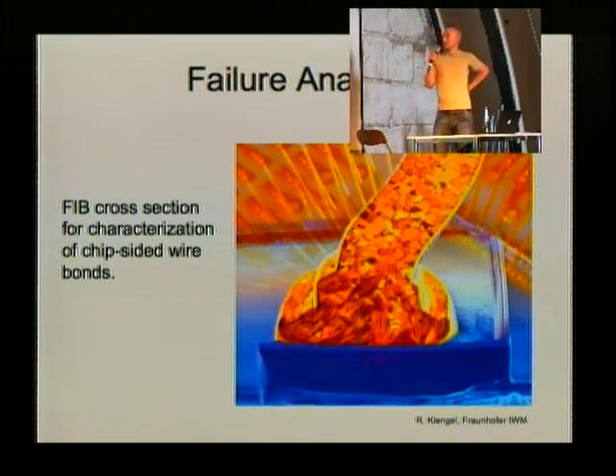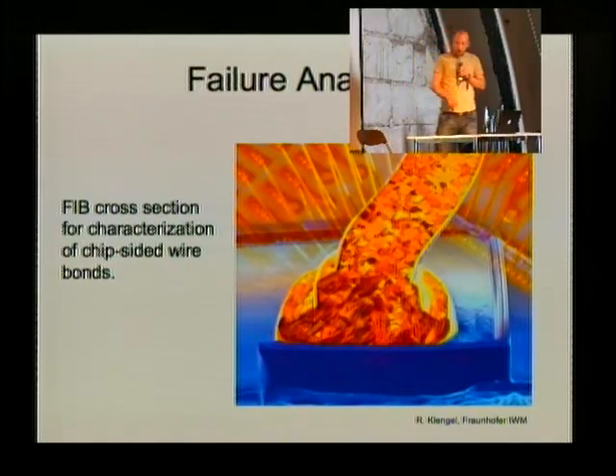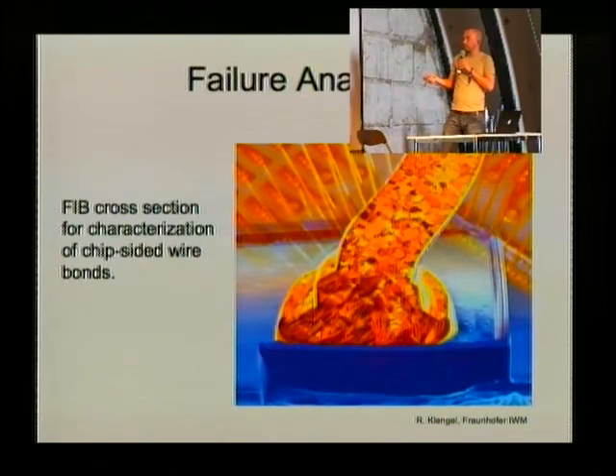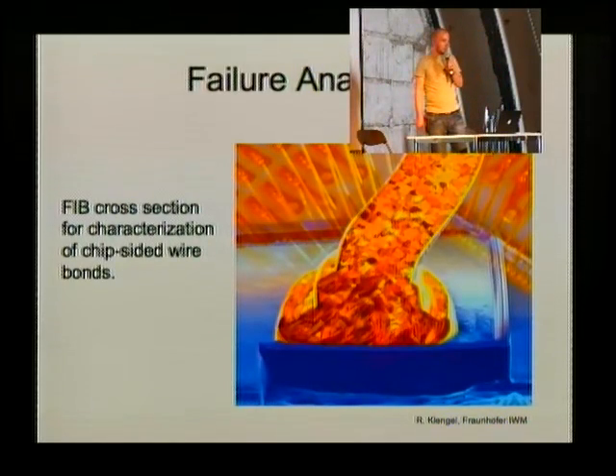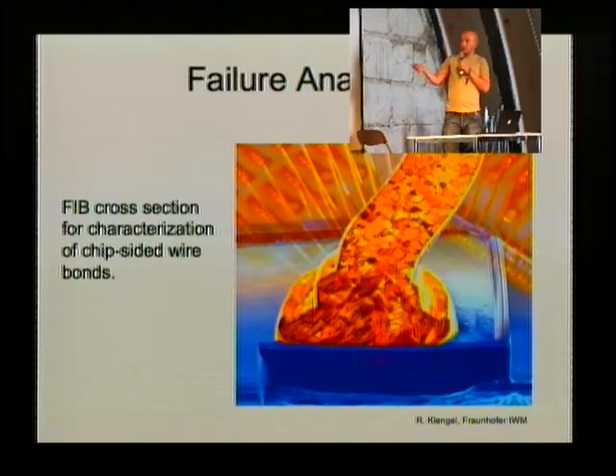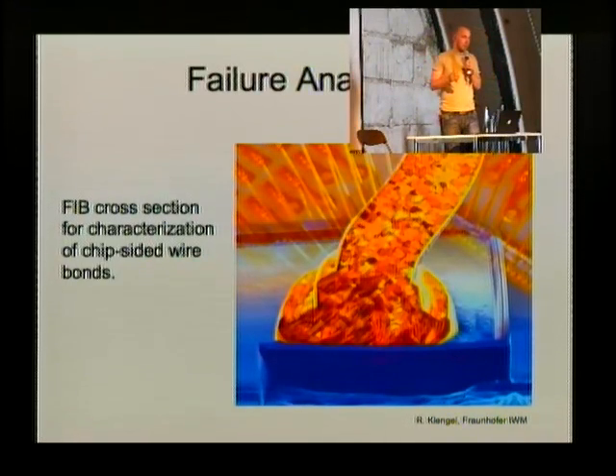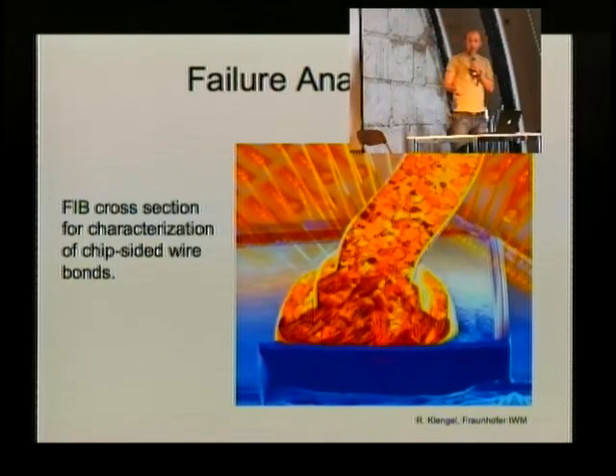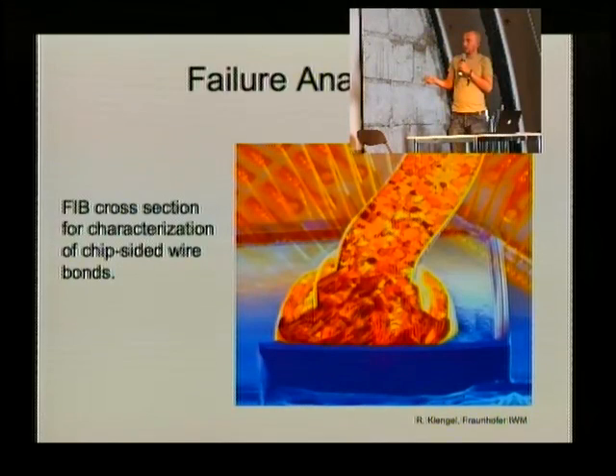So, why is it so nice for failure analysis? What we see here is the chip-side bond of a gold wire, and there are many factors governing how this wire bonds. This is a common cause of device failure, that one of these wires breaks or gets detached from the substrate. So the FIB allows you to basically cut the soft wire and cut through the very hard silicon without changing the surface. So you can nicely see here you get a very clean cut, you get the cut exactly where you want it to be. And you can later have a very close look at this contact surface between the bond and the chip.